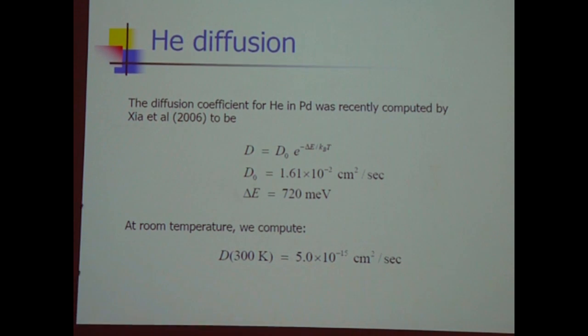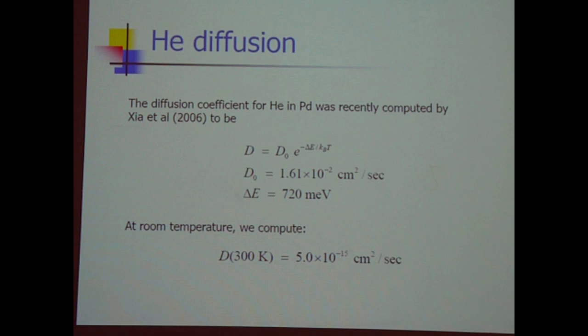But I mean, question. Doesn't that also drive out potential atoms that might react when you heat it up? Maybe you don't take my analogy quite as much. I'm not getting rid of all gas, hydrogen, deuterium, helium-4. The idea is that if you can get the helium-4 out of the trap, then it's going to diffuse to the nearest surface. When it reaches the surface, it can leave.